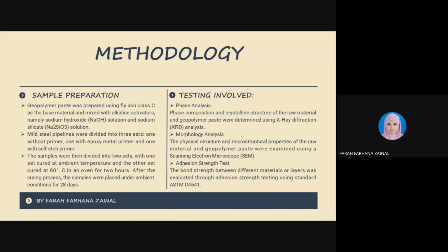So after 28 days, the testing for phase analysis, morphology analysis, and adhesion strength test analysis were involved. For phase analysis, phase composition and crystalline structure of the raw material and geopolymer paste were determined using XRD analysis. For morphology, the physical structure and microstructural properties of the raw material and geopolymer paste were examined by using scanning electron microscope, SEM. And the last one, adhesion strength test, the bond strength between different materials or layers was evaluated through adhesion strength testing using standard ASTM D4541.